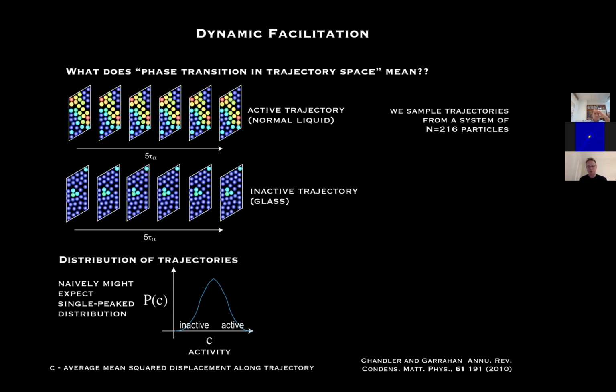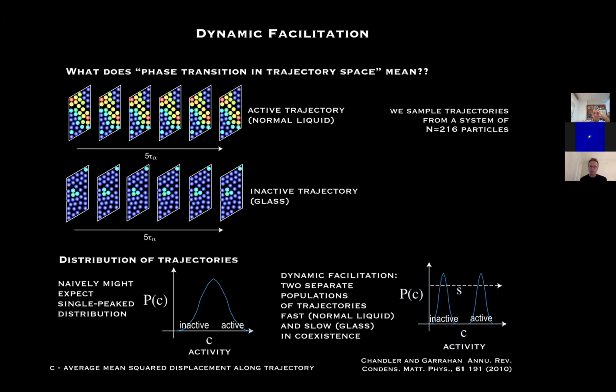And there's a distribution, some of them move, some of them don't move. The naive expectation might be for a single peak distribution. But actually, it turns out that what happens is a double peaked distribution under the right sampling. What this corresponds to is a phase coexistence of a so-called active phase of moving particles, on the top left of the slide, the upper trajectory, where the particles are moving and are brightly colored, and this is a phase coexistence with inactive trajectories, which are glassy.